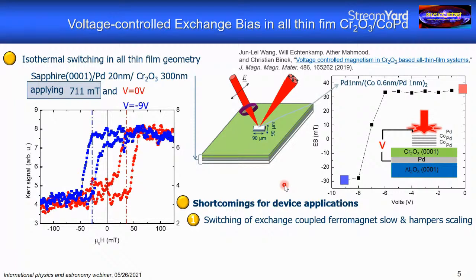Roughly speaking, qualitatively speaking, if you remove volume from the antiferromagnet, then the magnetoelectric energy that you obtain to switch the ferromagnet scales down with the volume loss, and it gets harder and harder to switch the ferromagnet. But more important is the contribution to the overall total energy of the system that comes from the exchange interaction between the ferromagnet and the antiferromagnet. So in one direction of the switching, this exchange interaction is supporting the switching. In the other direction, it is hampering the switching, making it harder and harder to switch the smaller you scale the thickness of the antiferromagnet.